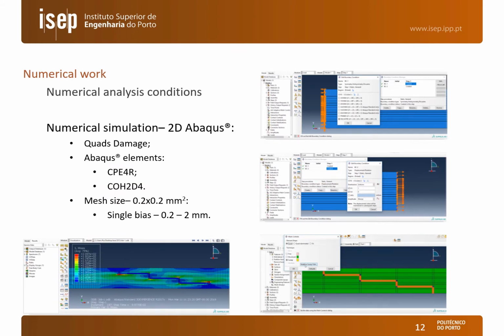The numerical simulations were carried out in Abaqus in 2 dimensions. We consider the quadratic stress criterion for damage initiation, an energetic criterion for damage propagation, and the elements that we used to model the adherents were CPE4R, these are plane strain elements, and COH2D4 cohesive elements for the adhesive. We can also see some details of the boundary conditions and of the partitions created to model the adhesive in the lower figure to the right, and an example of stresses in the joint during the loading.